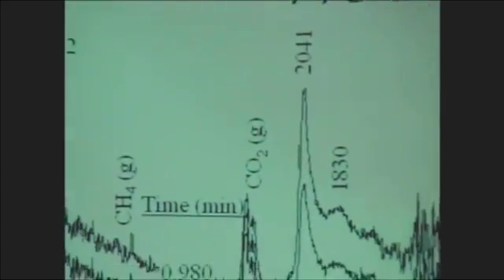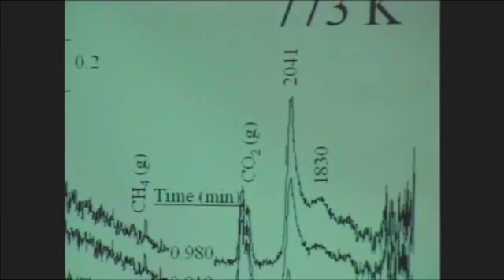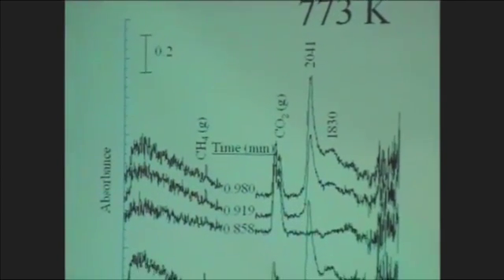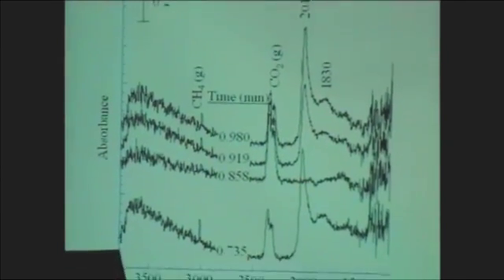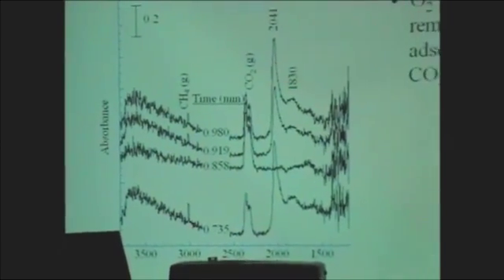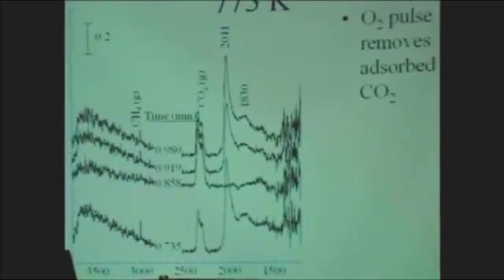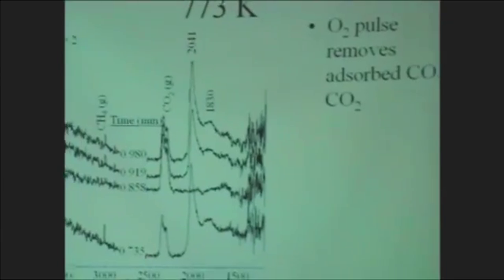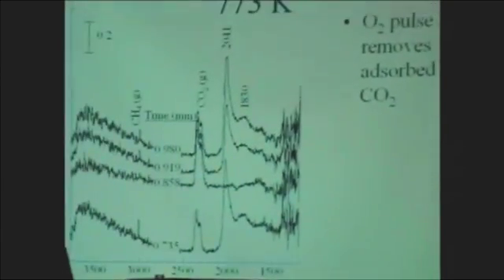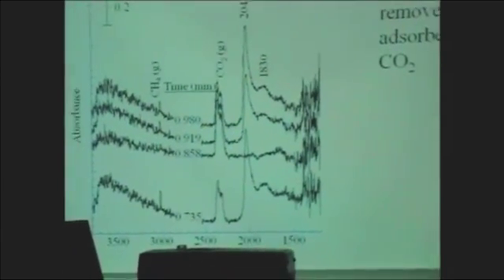The reason is, we like to keep the catalyst surface in the reduced state. We know most of the reforming reactions take place on the reduced catalyst surface. So if we put too much oxygen in, then we tend to oxidize methane to form CO2 and water. So we like to control the amount, sending a small amount of oxygen into the reactor.